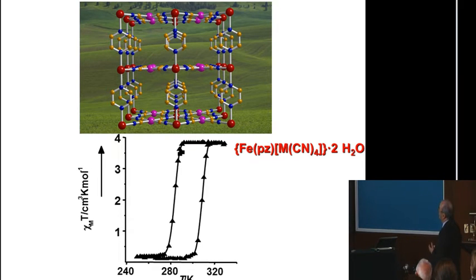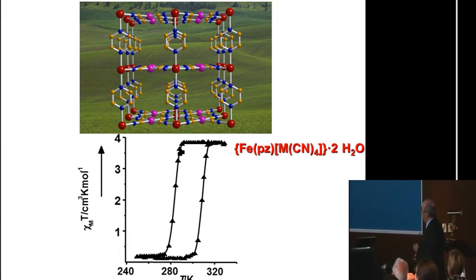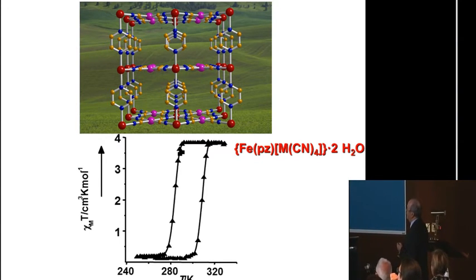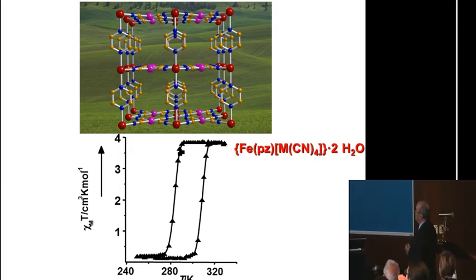So then the interactions between two ions here is quite strong because you have real bonds here, not hydrogen bonds. And that means that you have strong interactions. If you look at the experimental measurements of the property of the system as a function of temperature, you see that with this system you can have a hysteresis loop here. You have a first order phase transition with a hysteresis loop around room temperature. You see, around room temperature.